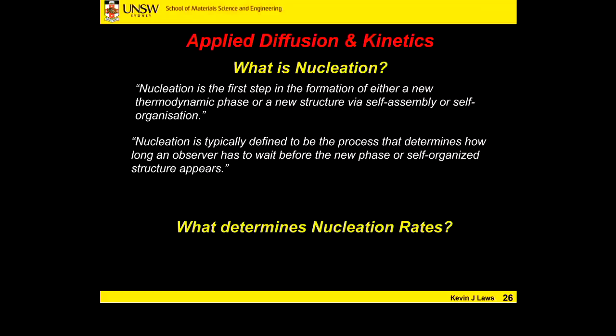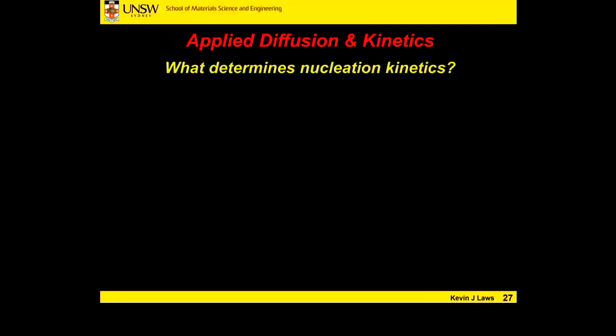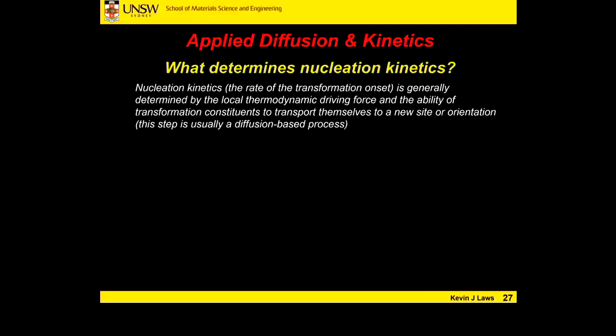Does anybody know what determines nucleation rates? It can be all manner of things. It usually is having a specific site where the activation energy for that nucleation event to occur is overcome so the reaction can start. So nucleation kinetics, the rate of the transformation onset, is generally determined by the local thermodynamic driving force and the ability of transformation constituents to transport themselves to a new site or orientation. This part of the step is usually diffusion based.